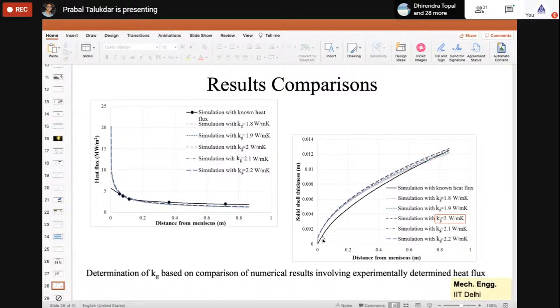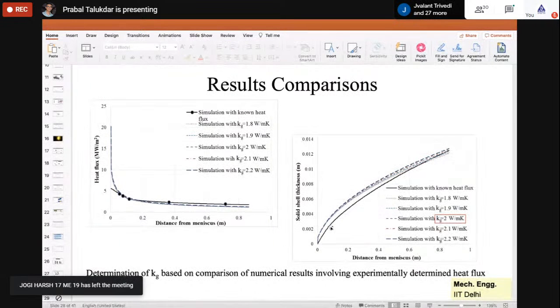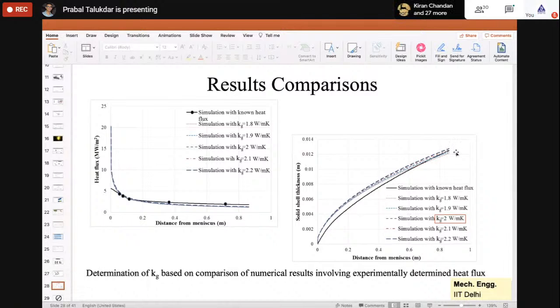to be the best one, because we have also compared with the solidified shell thickness. And if you see, the black color is the simulation with known heat flux from experimental data. So at the end, the solidified shell thickness matches very nicely when we assume Kg is equal to 2 watt per meter Kelvin. Although all are good, 2 watt per meter Kelvin is very close at this portion. Here they are not matching much, but at the outlet of the mold, matching is more important, because that basically gives you the prediction of the solid shell thickness. So that is why it is considered to be the best one, right?